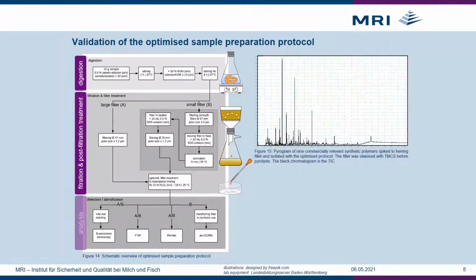For preliminary in-house validation, we applied the more complicated version B, as it was necessary for pyrolysis GCMS in our lab. First, we tested if polymer identification was possible after isolation from fish fillet with pyrolysis GCMS, as shown here exemplarily. Therefore, we spiked fish fillet with commercially relevant plastics.